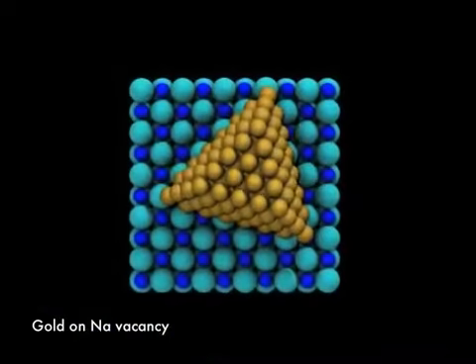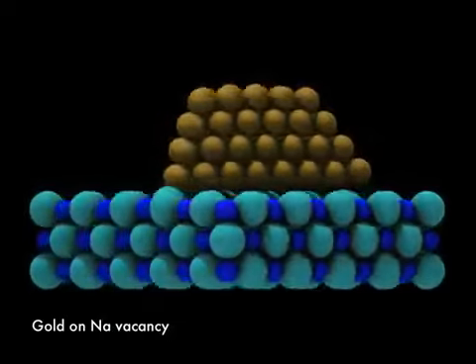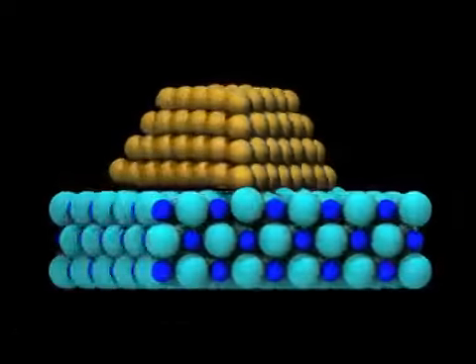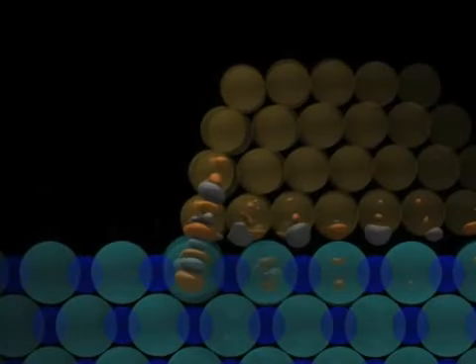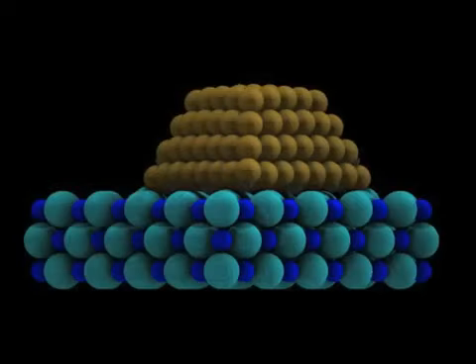We find especially that if a cluster is paired with a sodium vacancy, it bonds to the surface only at one of its edges. Here we see the electron glue, which attaches the cluster edge to a row of chlorine ions on the surface. In this kind of configuration, the cluster likes to slide only in the direction parallel to